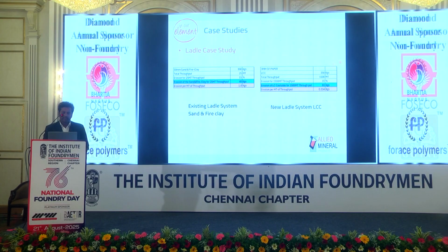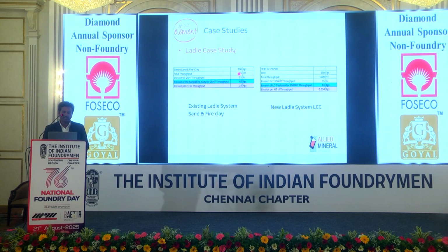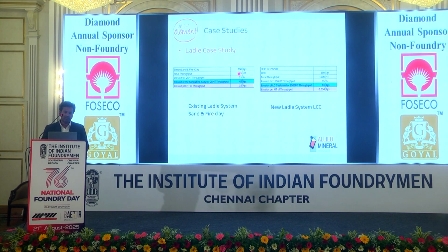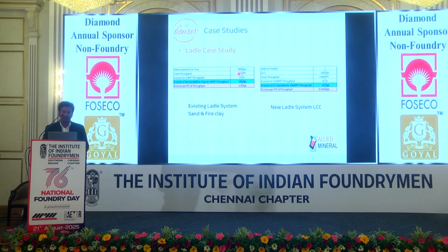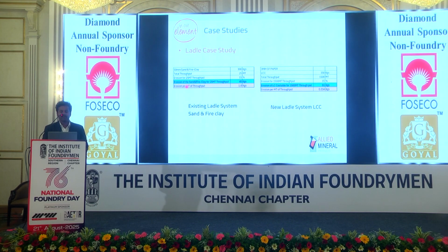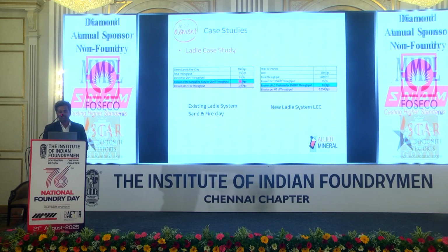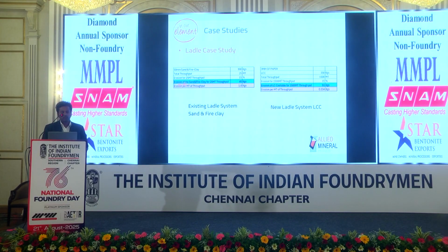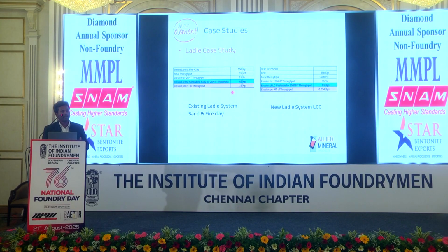So here in their existing system, they used to use 300 kg of sand and fire clay. So their total throughput is only 25 metric ton. The erosion after 25 metric ton is like 15%, which is like 45 kg of sand. So erosion per metric ton of throughput is like 1.8 kgs.